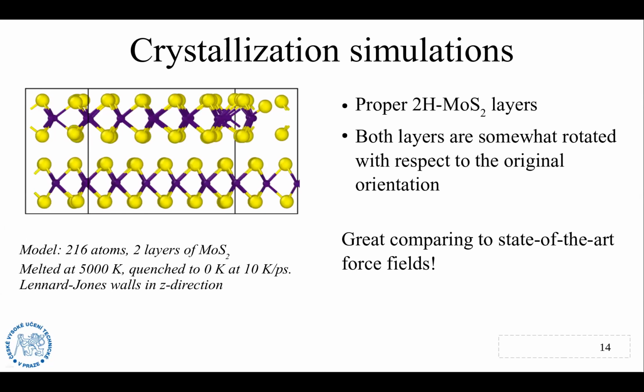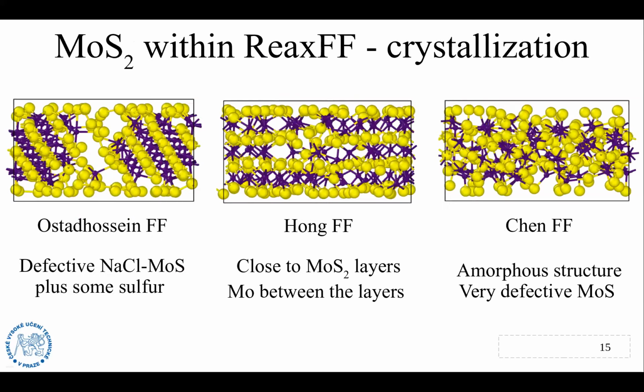So I run crystallization simulations in this relatively constrained two-layer setup, and I get the right 2H MoS2 layers, though they are a little bit rotated from the expected setup. And well, again, comparing to the state-of-the-art force fields that were not producing the MoS2 layers at all, it's pretty notable progress.